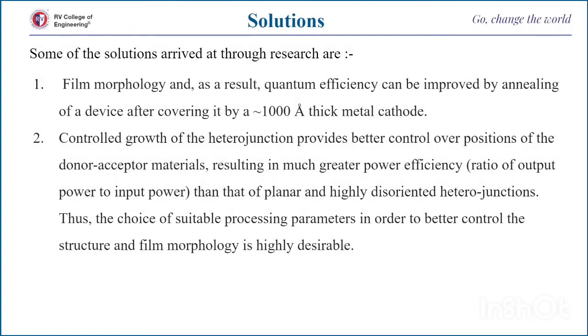Some of the solutions arrived at through research for these challenges are: film morphology and quantum efficiency can be improved by annealing of a device after covering it by approximately 1000 angstrom thick metal cathode. Controlled growth of the heterojunction provides better control over positions of the donor acceptor materials, resulting in much greater power efficiency than that of planar and highly disoriented heterojunctions. Thus, the choice of suitable processing parameters in order to better control the structure and film morphology is highly desirable.